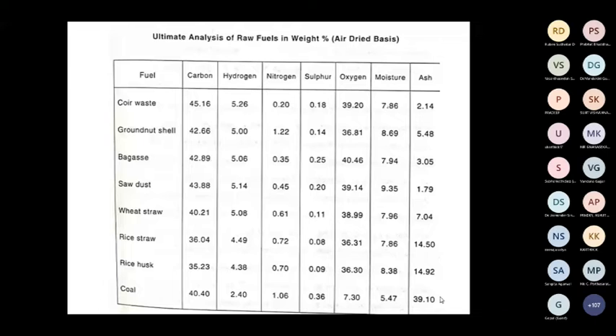So the oxygen content is almost 5 times that of coal. You have more than 35% oxygen content.